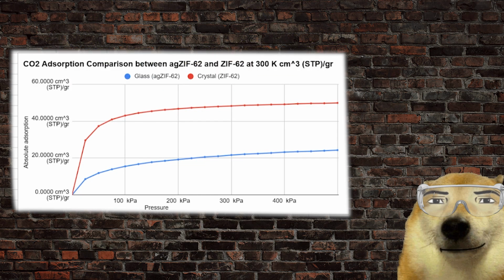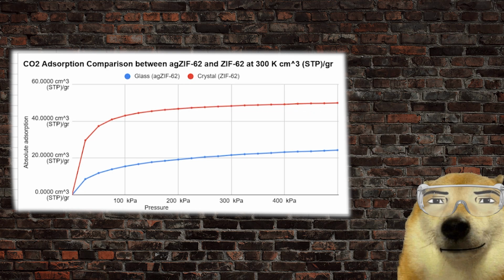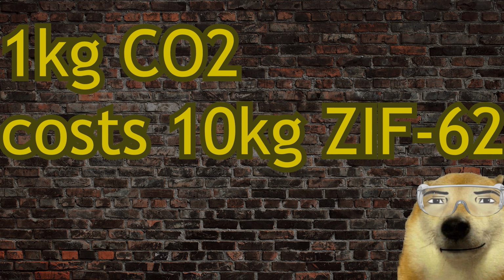Quantitatively, the crystalline ZIF-62 saturates at around 5 atmospheres, reaching roughly 50 cubic centimeters of CO2 per gram of framework, which is about 0.1 grams of CO2 per gram of material. So, roughly speaking, capturing 1 kilogram of CO2 would require about 10 kilograms of ZIF-62.